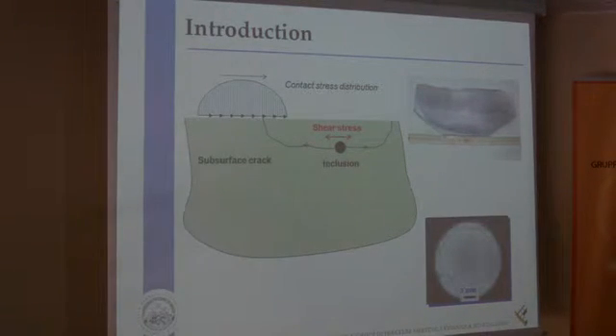Subsurface crack nucleation and propagation is typical of the rolling contact fatigue phenomenon in hard steel. In particular, crack nucleation is favored by the presence of inclusions like oxides and sulfides, while subsequent propagation happens mainly by shear mode, mainly mode 2 in this case, and is led by orthogonal shear stresses. The crack can go a long way before branching towards the surface and causing severe and sometimes catastrophic damage like deep shelling or piece crashing.